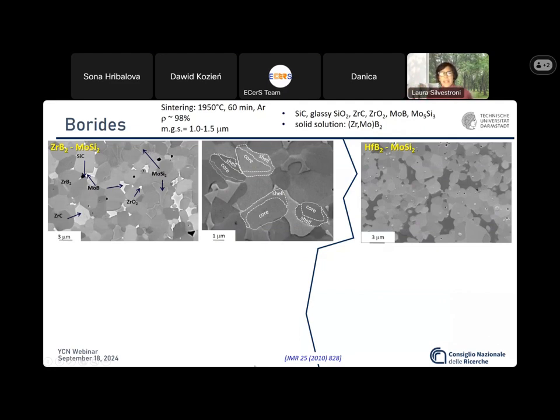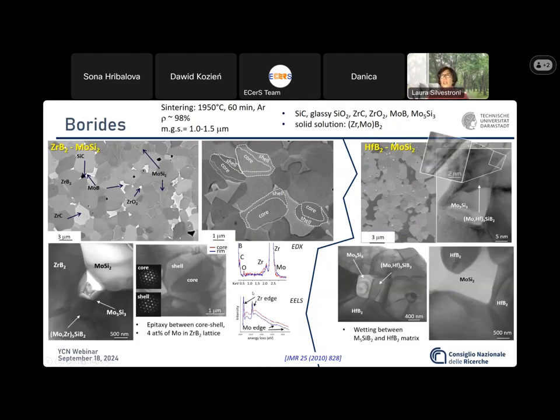We did the same on the borides, and here for the first time we identified the core-shell structure, which is a particular morphology of the grains, where the core is the original boride, zirconium diboride, and the shell is a solid solution that grows around the core and contains the element that we added with the sintering additive, molybdenum in this case.